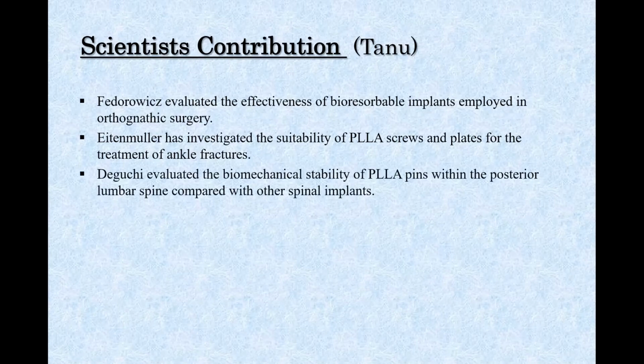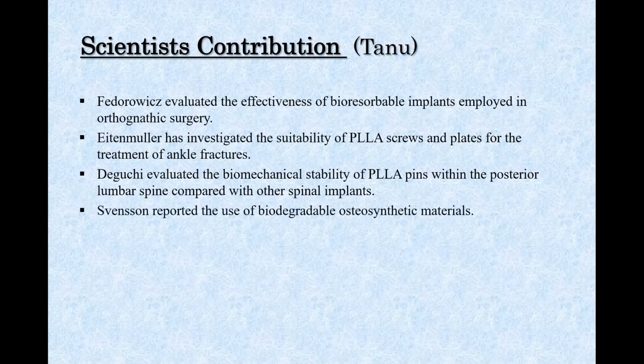Deguchi and others evaluated the biomechanical stability of poly-L-lactide pins in the posterior lumbar spine in comparison with other spinal implants, and showed that the poly-L-lactide pin construct provided improved stability to the spine, although it was not as stiff as the screw construct due to the sliding motion of the pins during testing. Svensson and others reported the use of biodegradable osteosynthetic materials in 50 children with transphyseal or osteochondral fractures, 2 patients developed non-union of articular radial head fractures, possibly related to a foreign body reaction.